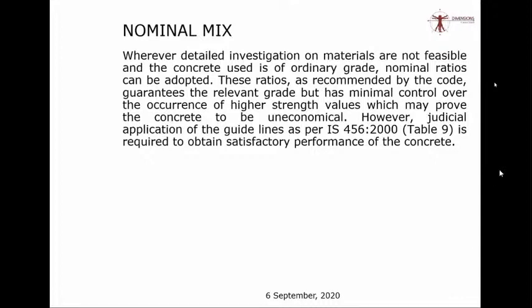So the nominal mix is only a guarantee of the minimum strength you will attain. So M20 adopted through this nominal mix table in your IS 456 need not always be M20. It can even sometimes be M30, or I have experienced M35 also in some cases. This is the table where you find the information regarding the nominal mix for concrete in your IS 456. It is table number 9, which says that